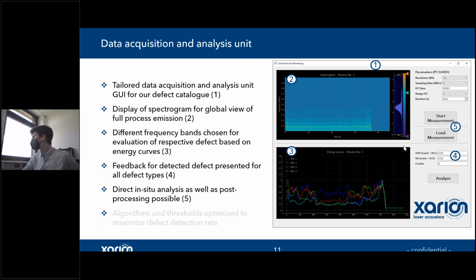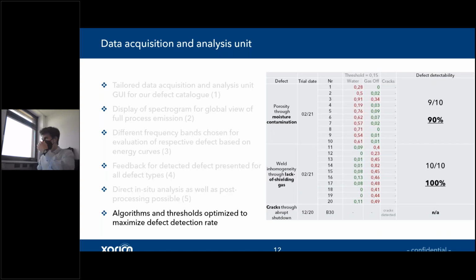And then here in this box, you get the output or the evaluation result. Again, here are our 3 defined defects, and you are able to adapt the thresholds according to your given process, and it allows you to directly see the defect detection rates. So we did cross checks, and in that test run, we had 10 samples with pores or with moisture contamination, because that was how the pores are provoked. We had 10 samples with the lack of shielding gas, which results also in a very faulty weld. And of course, we had also the cracks.